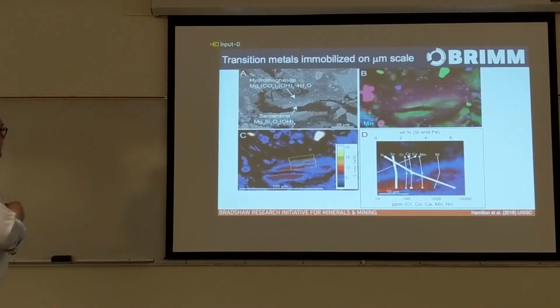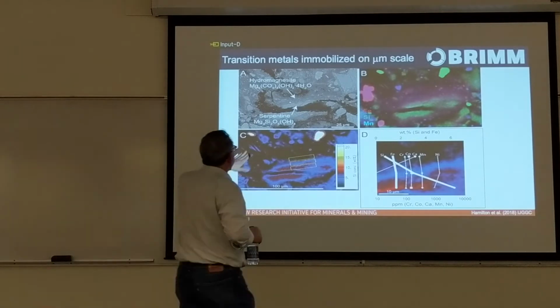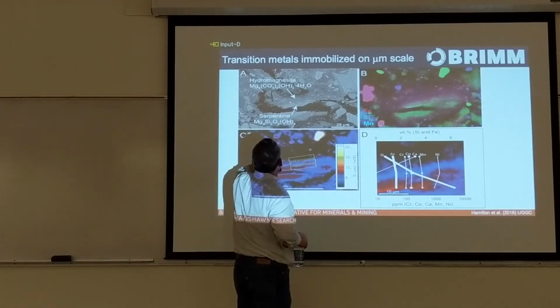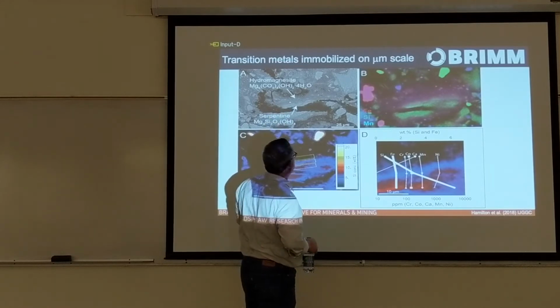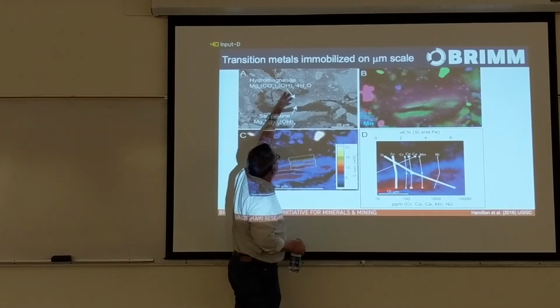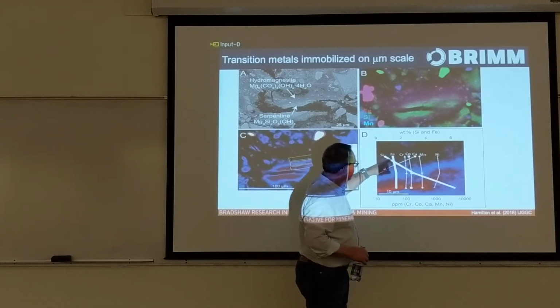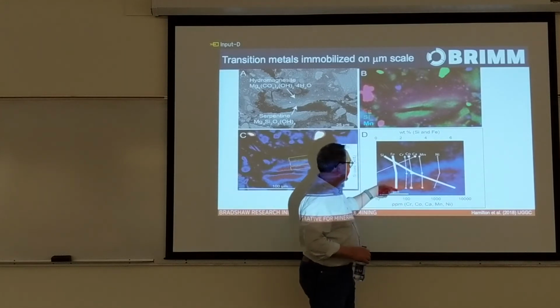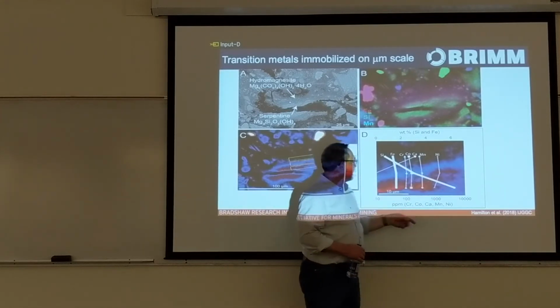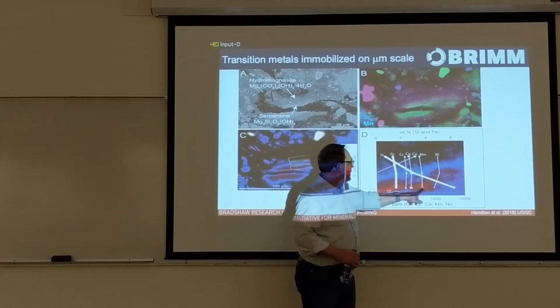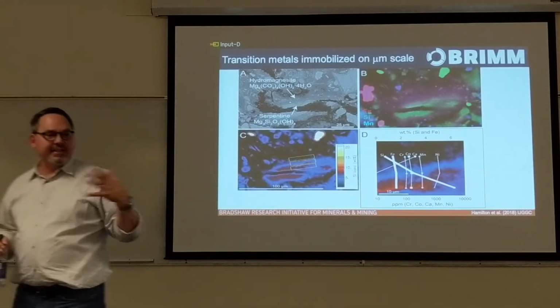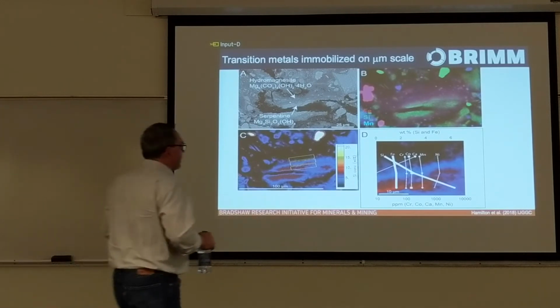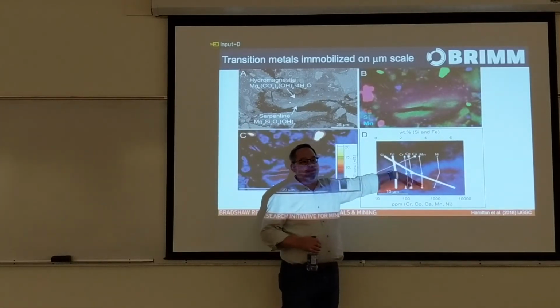This is work that Sasha Wilson and her students did. This looks at reactions that have happened in the tailings pile where serpentine has been partly carbonated. So you essentially have hydromagnesite replacing serpentine, and this here really just shows 3 spots in here and the relative movement on this scale. Here's the iron, chrome, cobalt, manganese, and nickel abundance. And the important thing to show here is we're going from silicate to carbonate. The manganese, the nickel, the cobalt, and the chromium contents are constant. We're replacing these minerals and encapsulating the toxic metals in the carbonate that replaces them.